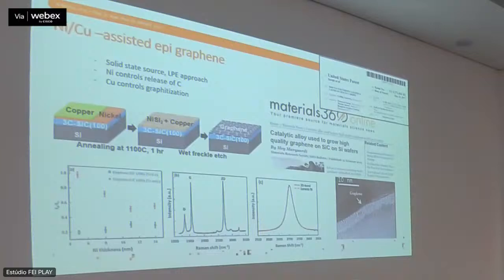And this was key to the process, because what happens is that the nickel, when you heat up the structure, will tend to combine with silicon carbide and silicon, forming silicides. The copper doesn't really form stable silicides, but it is a very good agent for the graphitization of carbon. So these two materials, this alloy of metals working together, turned out to be really beneficial. You can see that here: remember the D band, you want to have it as low as possible. For example, if you used only nickel, you can see here that we would have an ID/IG ratio that's still pretty high, so not really very good quality and large grain size. But if you mix the nickel and the copper, you can reduce that ratio, not completely, we don't want to do miracles because you see the type of thing we're working with, but reduce it down to 0.2.